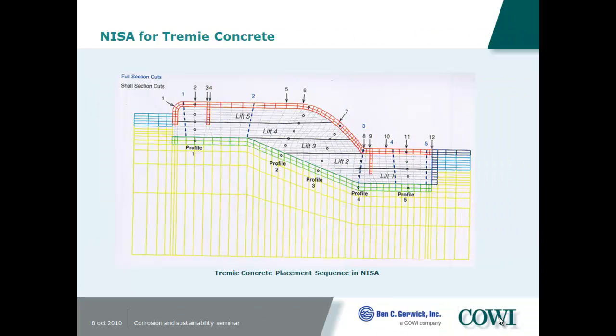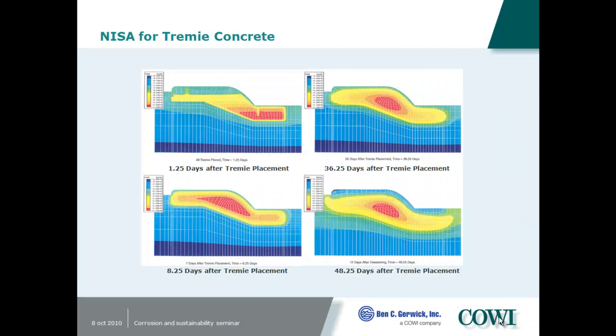So we did a non-linear incremental structural analysis. All the properties of concrete are non-linear at early age, and so we have to vary the stiffness of the concrete, the Young's modulus, so the strength is changing, the tensile strength is changing, and the heat generation patterns go into the analysis on the computer. We have to match the sequence of construction with the different lifts going in at different times, and simulate the ambient temperature from the river water during the summer and the winter to match our placement plan. They're placing now in the fall.